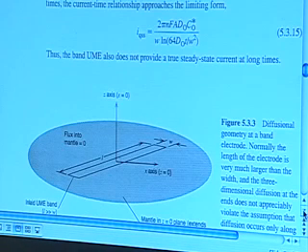His only problem is the way he did that when he broke it is that then he had to eliminate the variations in the glass that was cracked, so he polished it with 0.05 micron alumina, which probably many people believe might well have roughened that 10 nanometer band of gold to be much more than 10 nanometers because of the alumina grit that was used to do the polishing. That's a debatable point, but you see the idea. Okay?